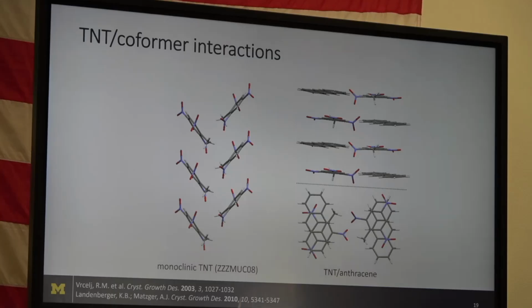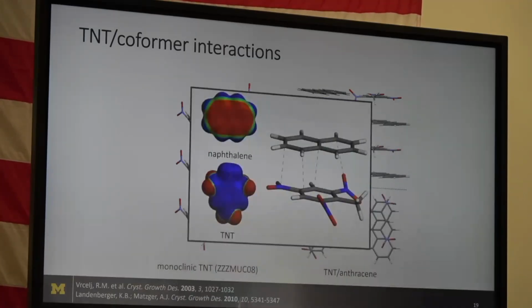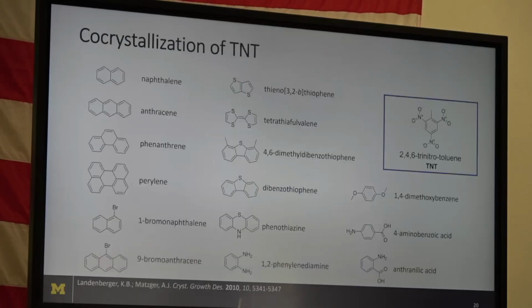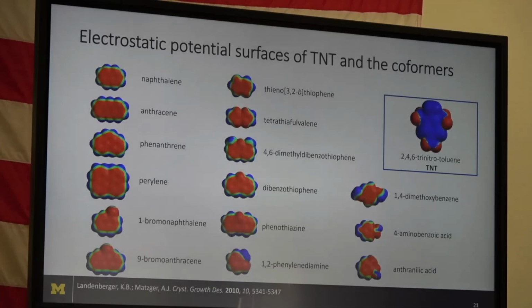And this is actually totally expected. And it can be predicted from the electrostatic potentials of these molecules. So TNT, because of those three nitro groups, is drawing electron density out of the pi cloud, and so it's making that electron deficient, whereas naphthalene has this nice electron-rich pi region, and so when those come together, we get pi stacking in the solid state. And indeed, for all of these successful cases, you can see a similar pattern. They all have an electron-rich, electron-poor, what you call a donor-acceptor type behavior that is favorable for co-crystallization.